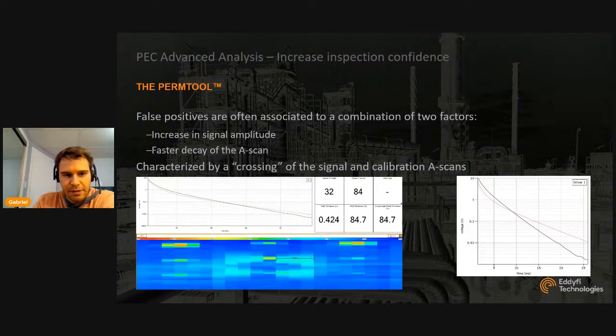False positives are often associated with a combination of two factors. And that's something we've noted through our R&D process. So here we've got a case of residual magnetization. As you move your cursor, and perhaps it's difficult for you to see on screen, over an area where there's no actual wall loss, but there's a change in magnetic properties that affect the wall thickness measurements from PEC, you see an increase in signal amplitude that's correlated with a faster decay of the A-scan.